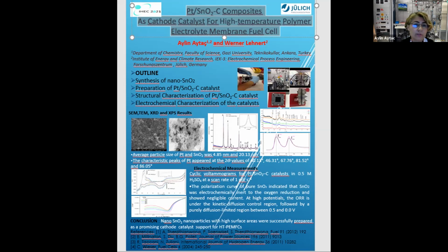Nano-tin oxide nanoparticles with a high surface area were successfully prepared as a promising cathode catalyst support for high temperature PEM fuel cell. Although oxide materials are considered as alternative supports to overcome the carbon corrosion problem in this type of fuel cell, the intrinsic semiconductor properties make it hard to apply them as actual electrocatalyst supports. But this tin oxide and carbon supported platinum catalyst shows good electrochemical activity for oxygen reduction reaction in cyclic voltammetric analysis, in both sulfuric acid and phosphoric acid. Thank you. Thank you, Eileen.